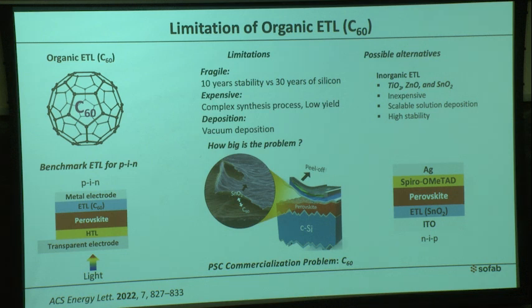The first problem is that a solar cell should have higher stability. But if you compare the stability of perovskite solar cell to silicon solar cell, the stability of perovskite solar cell is very low compared to silicon. That is due to C60. C60 is fragile whenever it comes in contact with external stress, such as high temperature or mechanical bending stability. It starts showing cracks and fracture.